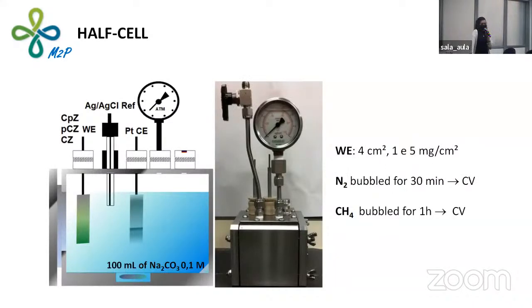Here there's a scheme of the half cell I used and a photo of it, and we can see that the working electrodes were CPZ, PCZ, and CZ. As reference, we used silver chloride, and as counter electrode, we used platinum. Nitrogen was bubbled for 30 minutes, and then we ran cyclic voltammetry, and then methane was bubbled for an hour, again running cyclic voltammetry. These results were subtracted one from another, and then we had a resultant voltammogram of which we took the current peaks, and found the potentials that we use to apply to form products.